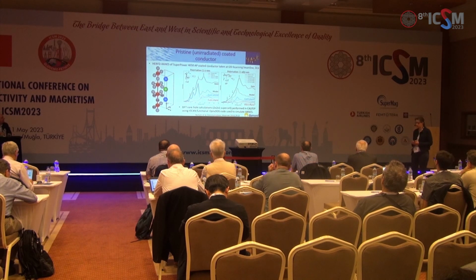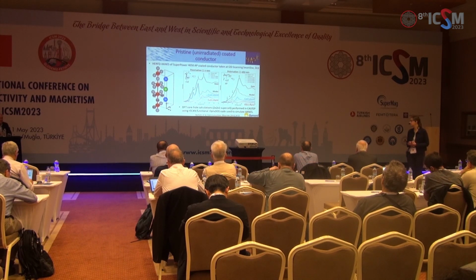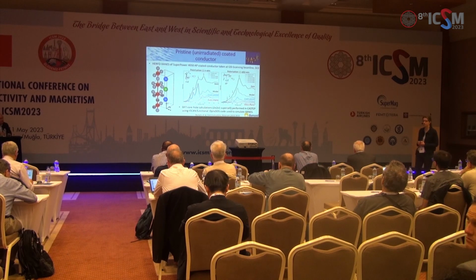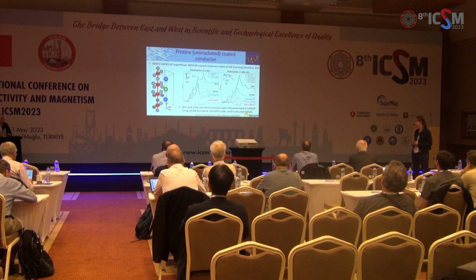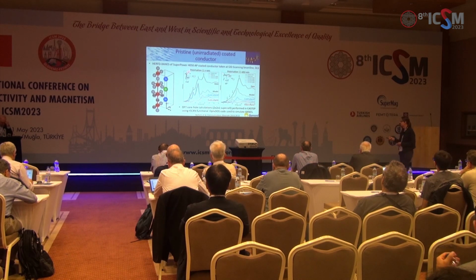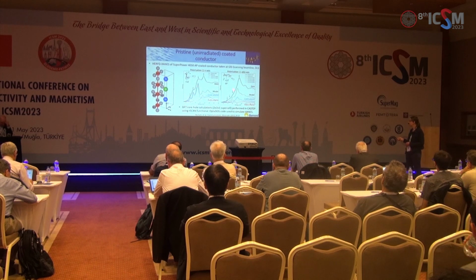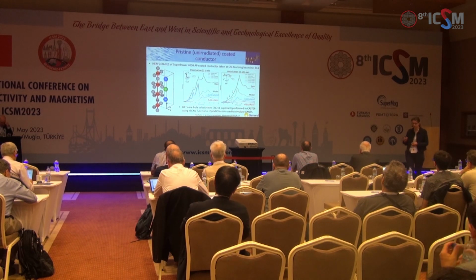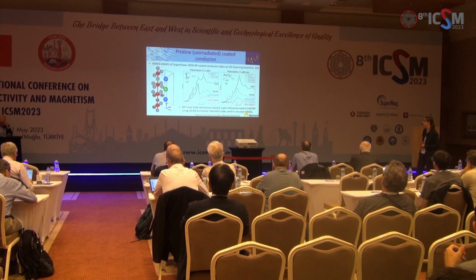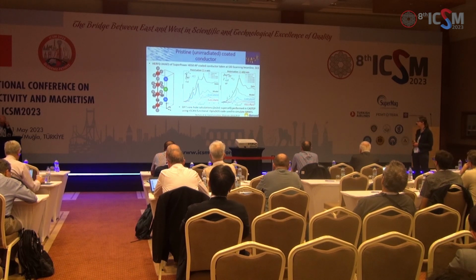So that we've got our polarization of those X-rays pretty much along the C-axis of the unit cell of the superconductor. So we're going to be probing bonds that are positioned along that C-axis direction with this graph. With this one, we put our X-ray in at different angles, so our polarization is roughly along the A-axis. So we're probing the bonds along the A-axis.